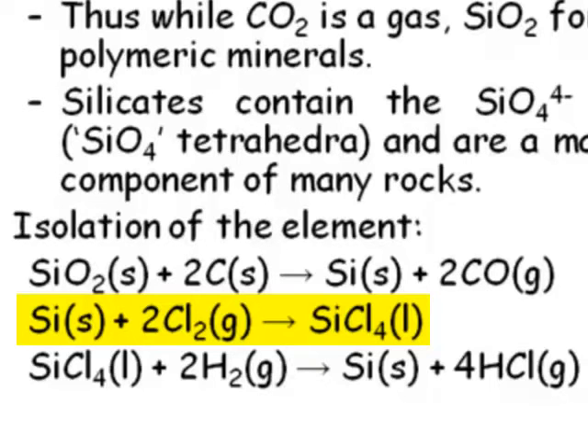And when you treat it with chlorine, silicon, being in group 14, favours a 4+ oxidation state, so you get silicon tetrachloride. The silicon is oxidized by chlorine to give us silicon tetrachloride. Silicon tetrachloride has a boiling point of, I think, around 50 to 60 degrees centigrade. It's a liquid which can be distilled. And if you have a liquid which can be distilled, you can therefore purify it. So you can purify your silicon in the form of silicon tetrachloride.